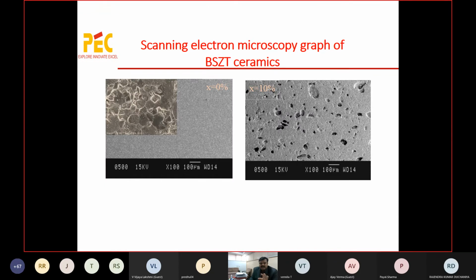So you can see clearly here for x is equal to 0 and x is equal to 10%. For x is equal to 0, there is no porosity, but for x is equal to 10%, you can see the porosity. Both are at the same magnification, that is 100 times. You can see the bar size, that is 100 micron. So in the 0%, there are no pores. For 10%, you will get the porous structure that is clearly visible from the SEM, scanning electron microscope.